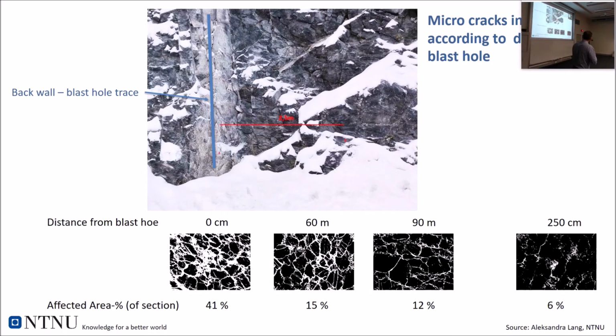So now this slide jumps a little bit away from quartz. This is an example from a limestone quarry, but it's just something we can use as well. Looking into microfractures again and how microfractures develop after blasting. So we see that this is a blast hole trace, and we have sampled along the profile away from the trace and see how microcracks are more highly concentrated close to the blast than away from the blast. And this is in the middle between two blast hole traces.